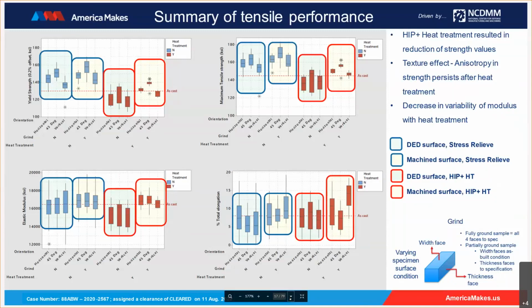Another observation was the surface condition of the specimens may influence the performance of the AM material, both heat treated and otherwise. And the other thing is the gauge orientation or the test orientation of the specimen relative to the horizontal, so the difference in these measurements is indicative of anisotropy in the material. And with the specific heat treatment that we've chosen here, what we've seen is that the anisotropy may not be completely removed with the specific heat treatment.